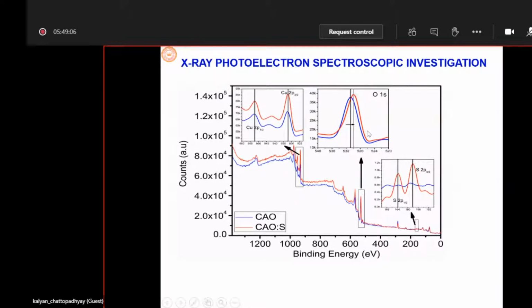And look at the oxygen peak. This is a correct chemical shift. The chemical shift actually decreases to lower binding energy, indicating that some of the sulfur has actually replaced the oxygen. Also, it is possible to quantify how much sulfur has been incorporated in the sample.